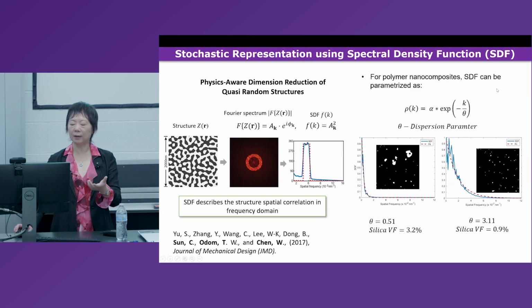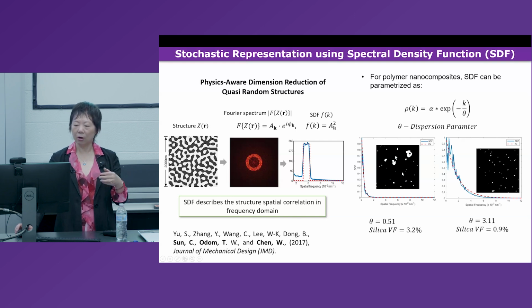For the nanodielectric material, my collaborator, Linda Schadler, her lab actually produced many of these materials using different processing conditions. And we did image analysis. Later on, we found that the shape of the spectral density function with 2 variables, one is the dispersion parameter and another one is the a coefficient, together with volume fraction, is sufficient to represent different types of microstructural morphology.